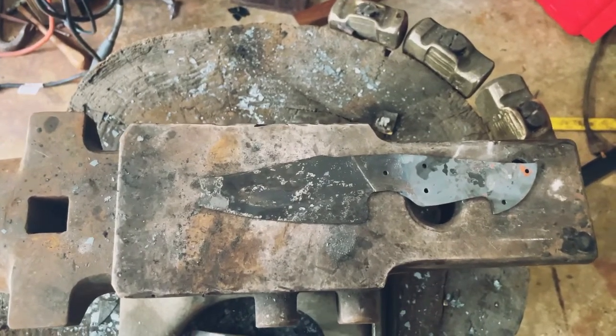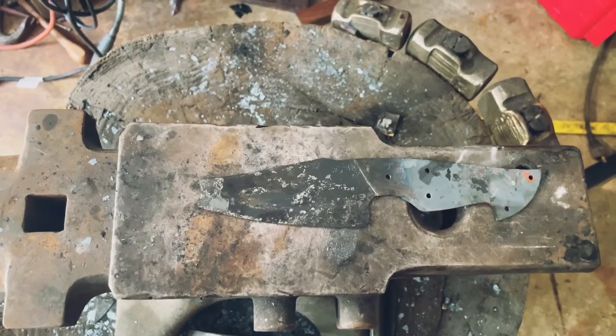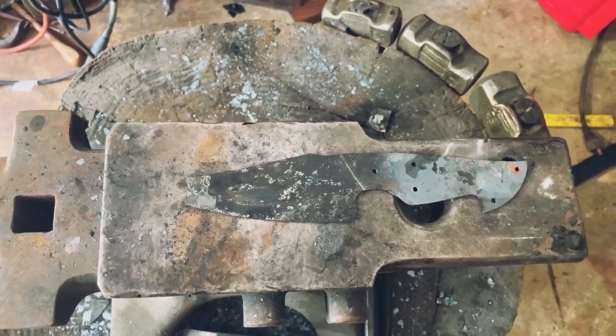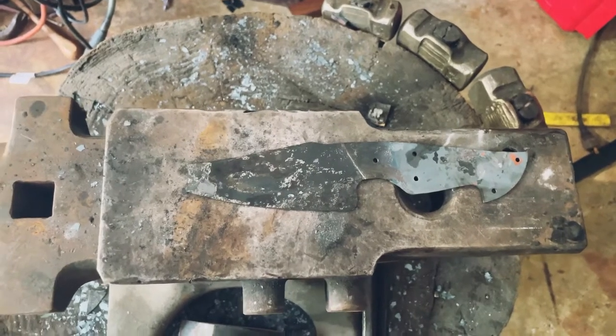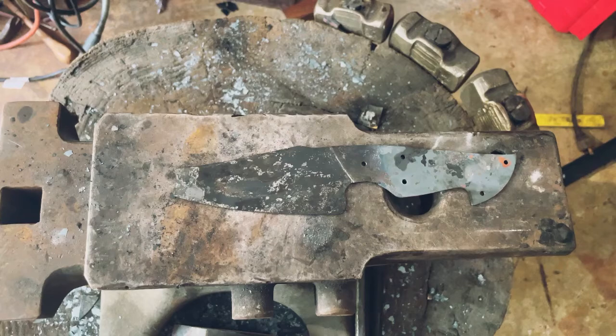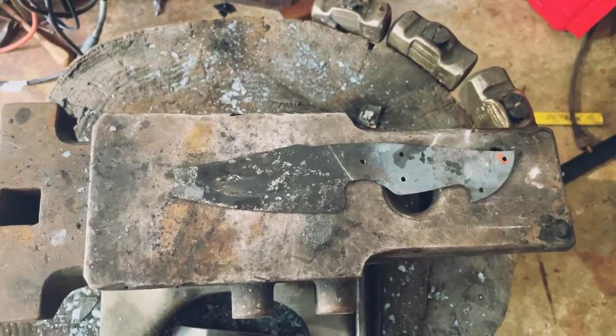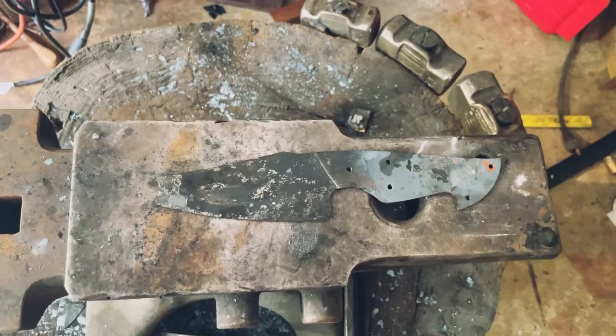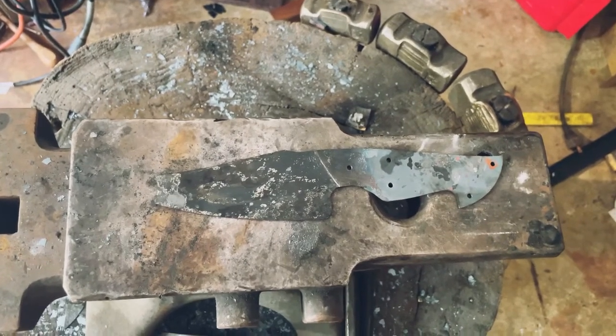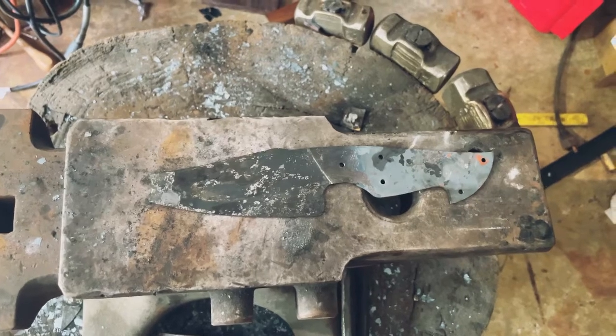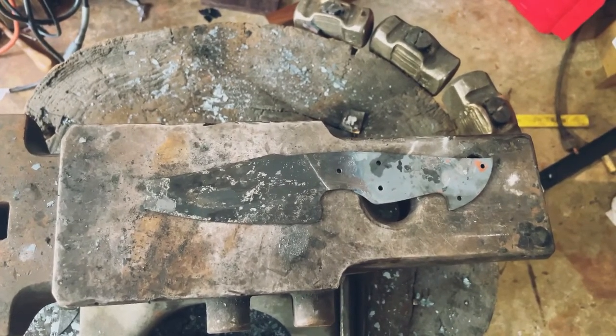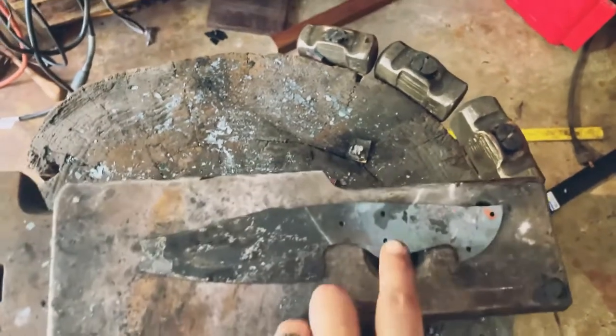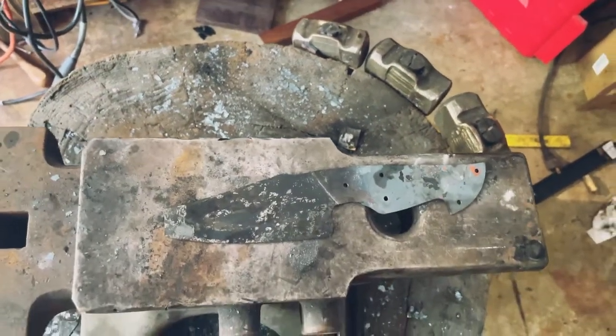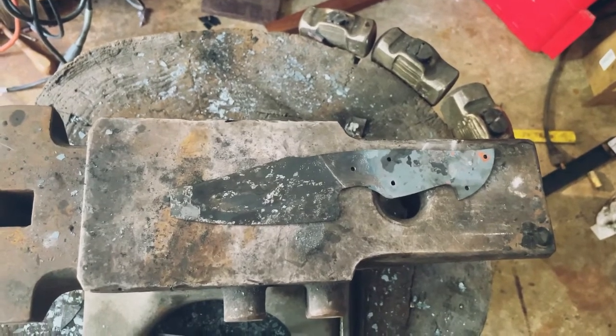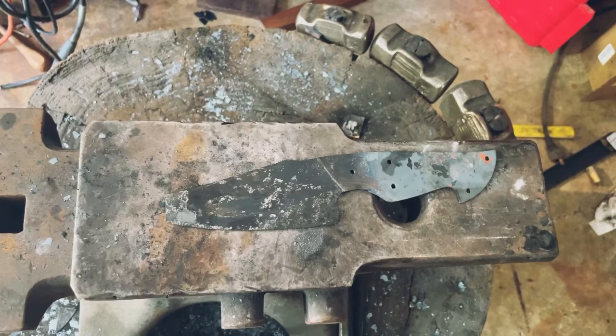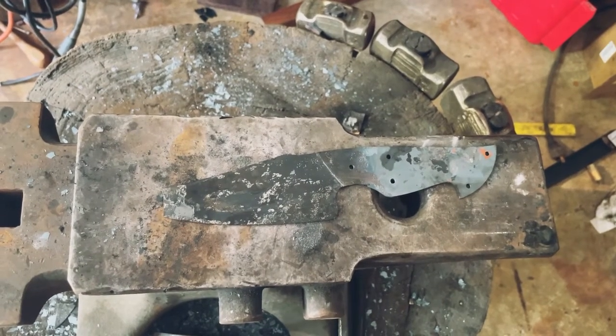this gives us a good opportunity to look at the grain structure of this little hunter. And we'll get a good idea of whether or not we did a good job with our normalizing cycles. So what we want to see is something that looks just like a solid gray mass in the center. If it looks grainy at all, if it looks like sand or anything like that, that is a bad thing. So if it's a solid gray mass and it doesn't look like there's any pores or anything like that, like it's a part of the steel, that's a really good thing, because that means that those grains became extremely tight, and you can't see the space in between them.